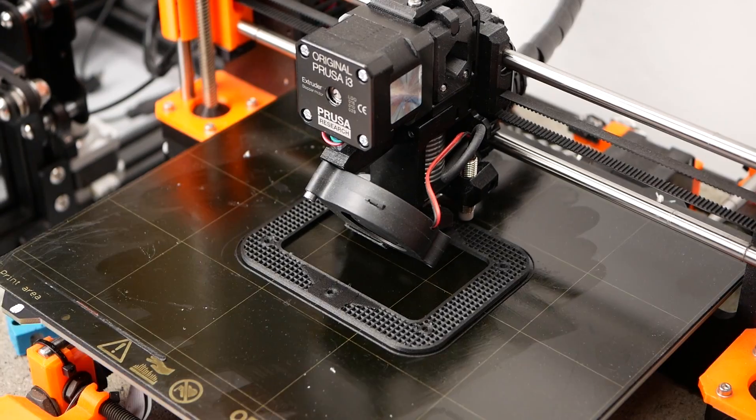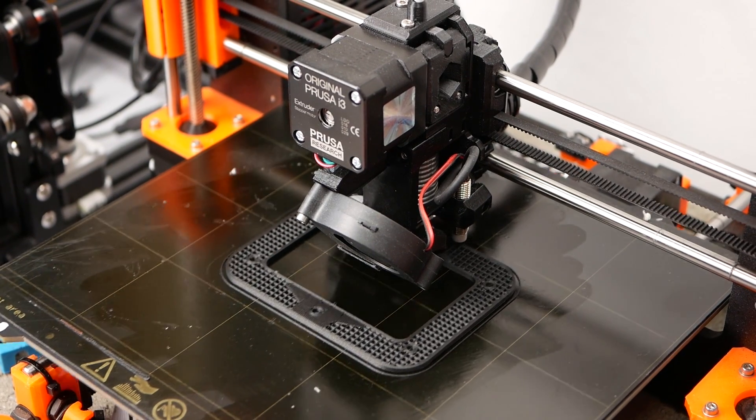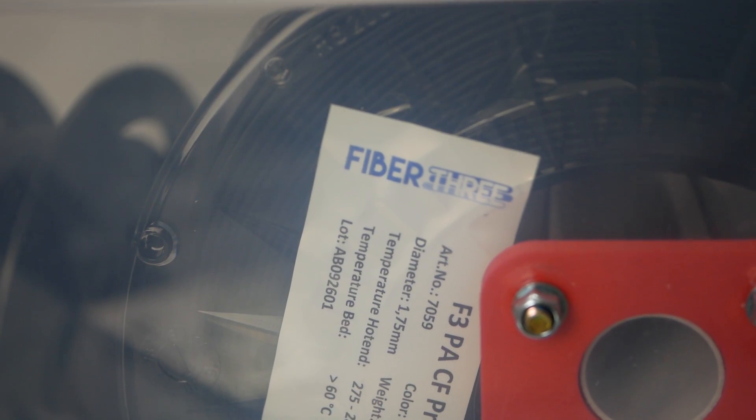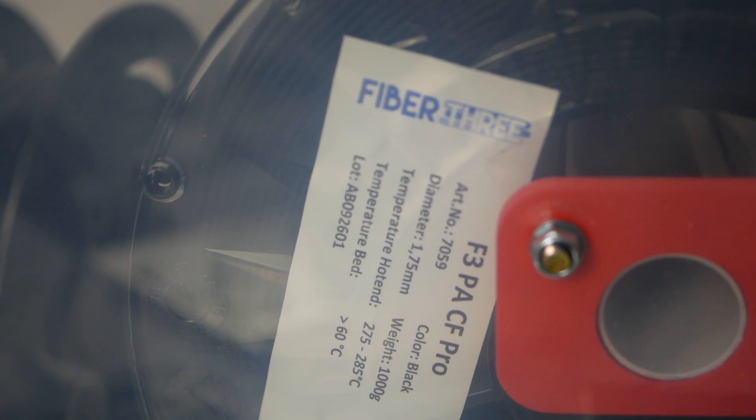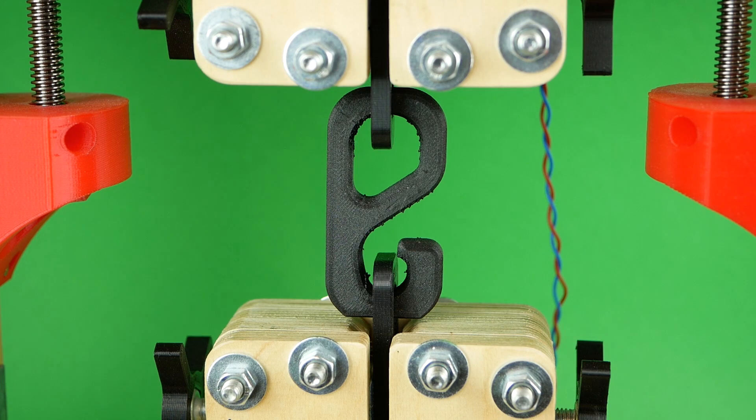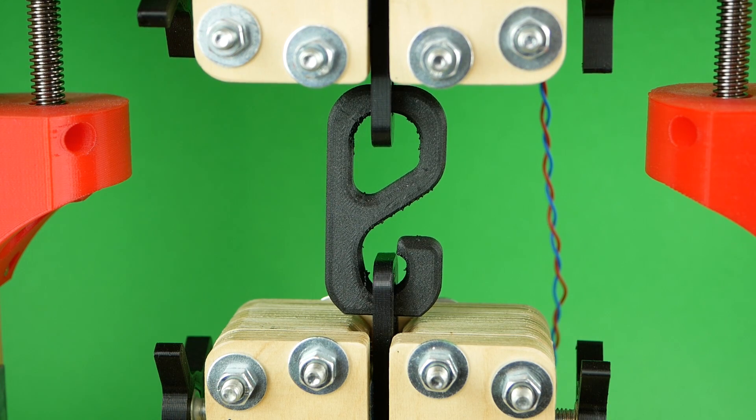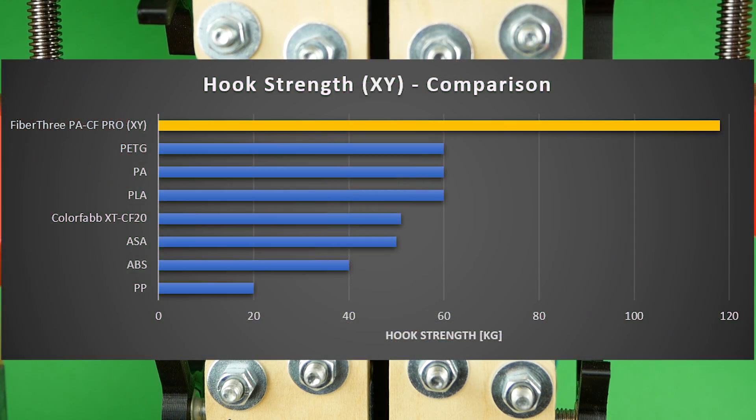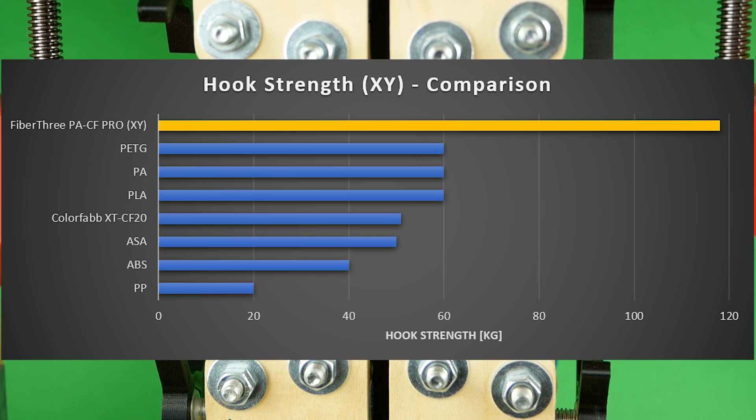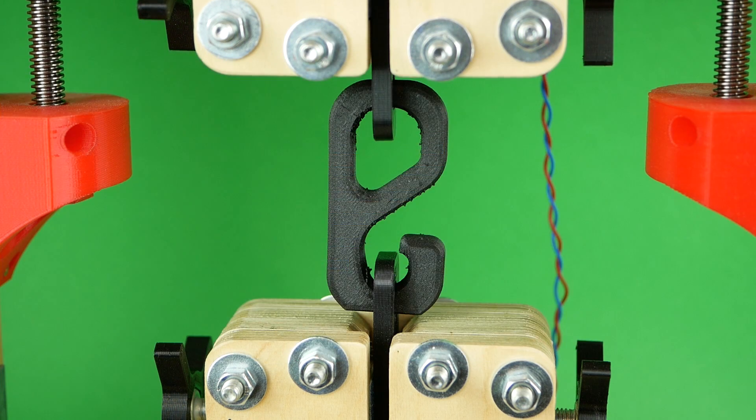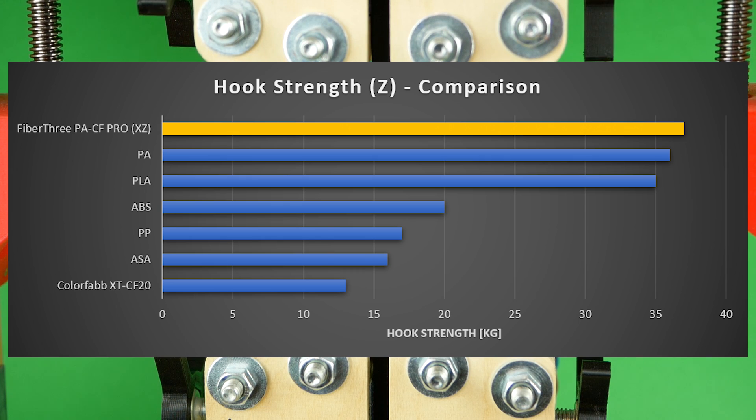And who would I be if I didn't use my 3D printers for that task? The German filament maker FiberThree sent me a roll of quite expensive but crazy strong carbon fiber and nylon filament. This stuff is printed at 285 degrees Celsius and is twice as strong as everything I have tested so far in my filament tests. Even the layer adhesion seemed to be at least acceptable.